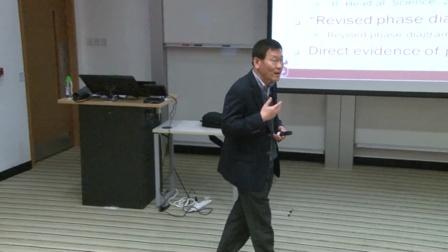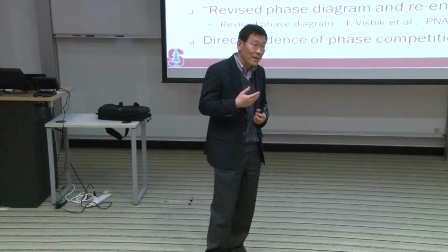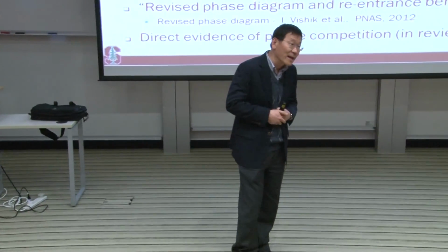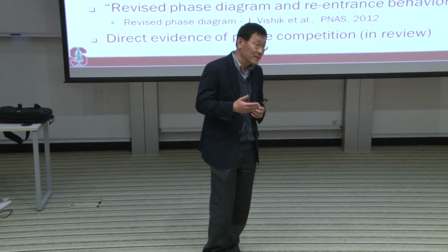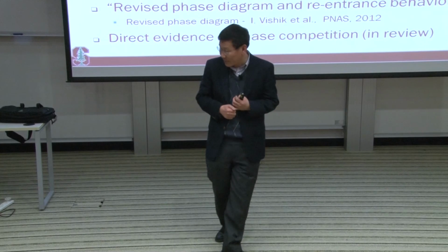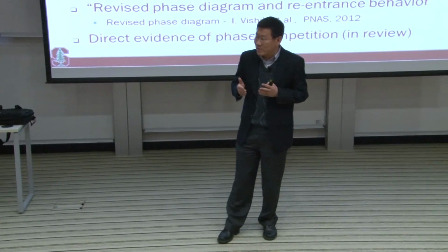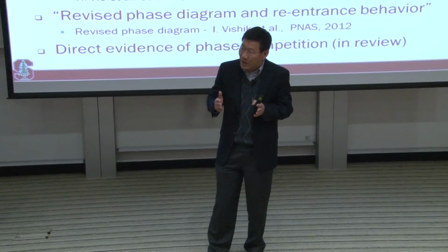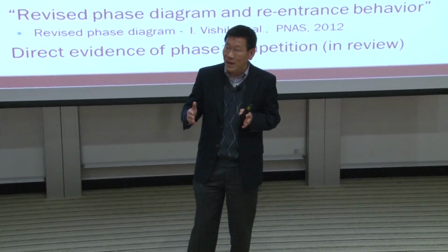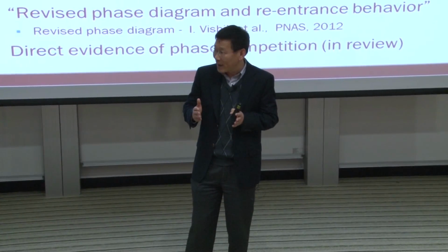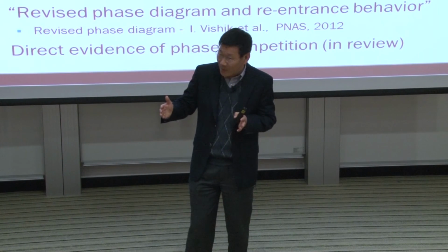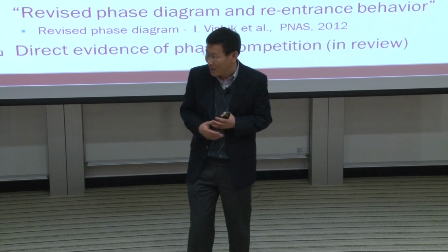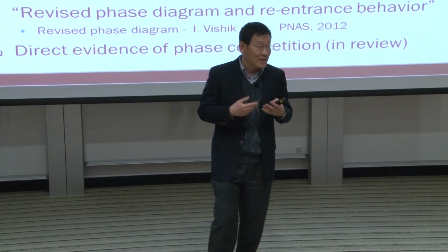It's still a highly debated issue. Based on the symmetry property analysis, we think it is most likely some form of density wave. Okay, and it's still a subject of study. You can say that it breaks the translational symmetry. It could be a simple type of correlated charge density wave, okay? But it could also be a pair density wave. That's a subject that still needs to be studied, but it's some form of density wave.